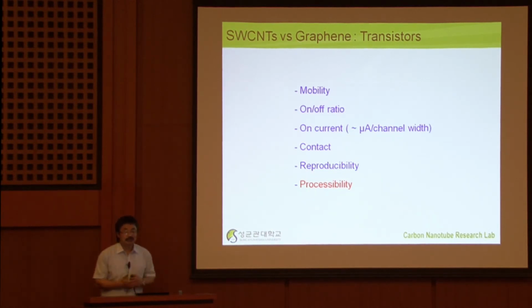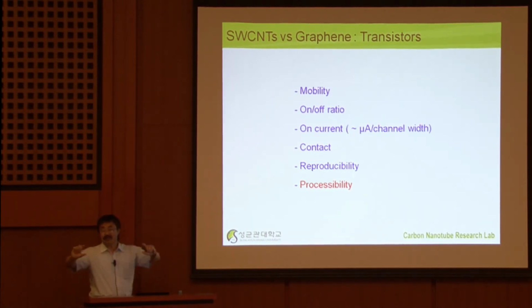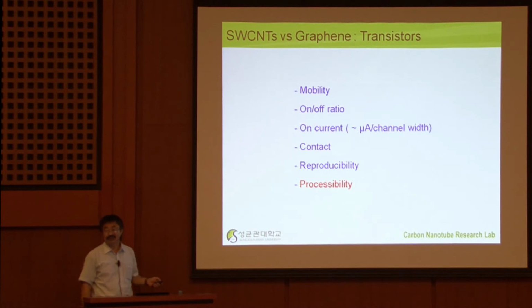Now, let's move on to transistor application. When we try to use carbon nanotubes or graphene for transistors, we have many different issues. One is, what is the mobility? Of course, the mobility for single nanotubes and graphene is really high. Compared to any existing material, this is the highest. Fine. What about the on-and-off ratio, which is crucial for switching the device? Carbon nanotubes is pretty okay. Graphene, to have a high on-and-off ratio, you have to make a nanoribbon. Means you have a graphene, and you have to make this width very, very narrow, less than 10 nanometer, which is another technical barrier for this use.